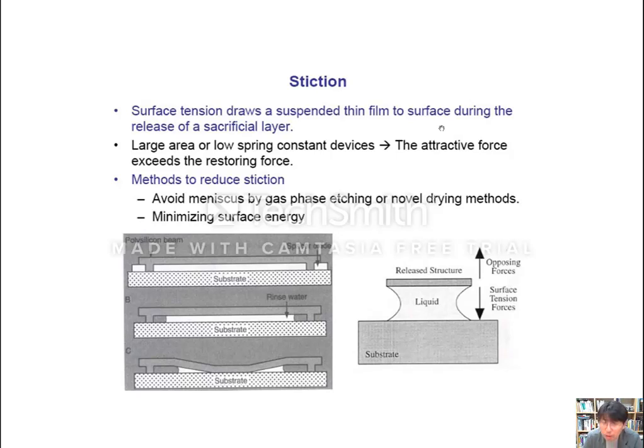So in supercritical drying, we replace the water with a solvent. Then they look at a certain path that you can go quickly from the liquid status to the vapor status at a particular temperature. So it does not take a long time, it can be done quickly. There is a special point around which the three statuses of the solvent can exist. So you can have a certain temperature and pressure, and you can manage it so that the evaporation path quickly goes through that supercritical point. With a machine to do that, this extraction problem can be avoided.